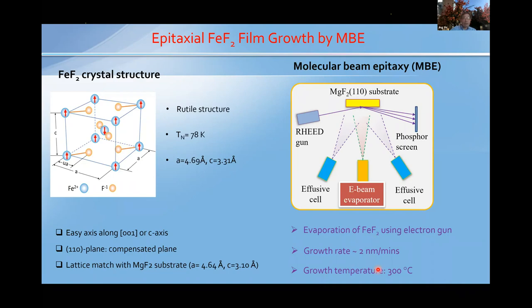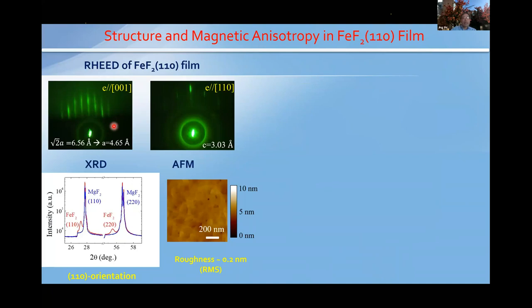Let me show you the RHEED pattern. During growth, we monitor the growth by RHEED. With the electron beam along different directions, we show this nice streaky RHEED pattern, and XRD shows that we have epitaxy. Iron fluoride is grown on this magnesium fluoride 110 oriented substrate. This is, I believe, 50 nanometer thick iron fluoride film grown on the magnesium fluoride substrate, and the RMS roughness is about 0.2 nanometer.